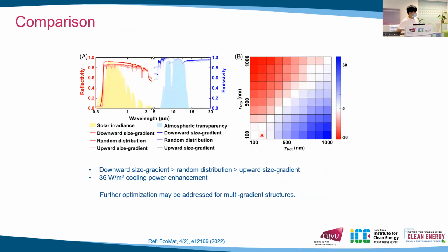And then we make a direct comparison for downward size gradient, random distribution structure, and upward size gradient. We can find that the best is the downward size gradient, and the worst is the upward size gradient. And the downward size gradient can provide extra cooling power up to 36 watts per square meter. But this is a very simple gradient structure. In practical coatings, we can find some more complex gradient structures that may further enhance the solar reflectance or the cooling effect.